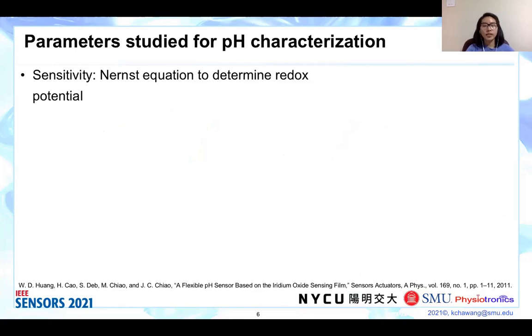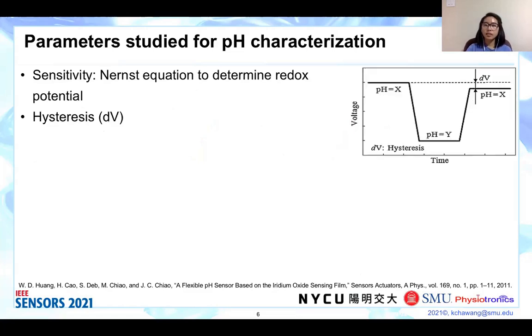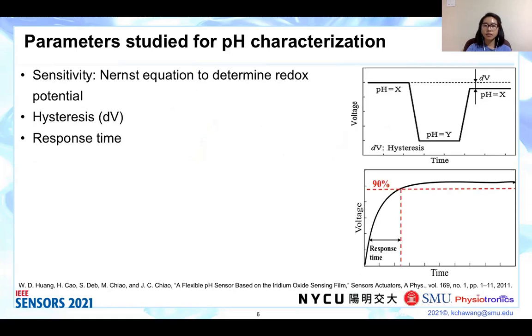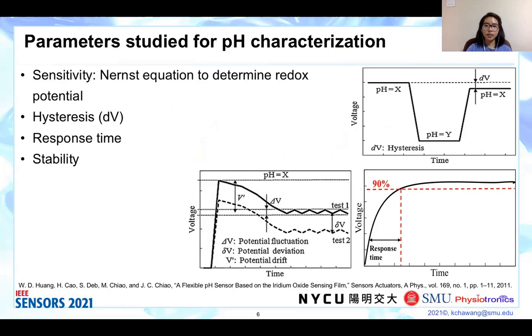For pH sensing characterization, multiple parameters were studied, which were also previously studied for Kapton-based pH sensors. First is sensitivity. We use the Nernstian equation to determine the redox potential. Second, hysteresis, which is defined as the standard error between settled potential at the same pH level. Response time is defined as time taken to reach 90% of the settled potential. Stability is intensively studied using 3 parameters, namely potential drift, potential fluctuation, and potential deviation.